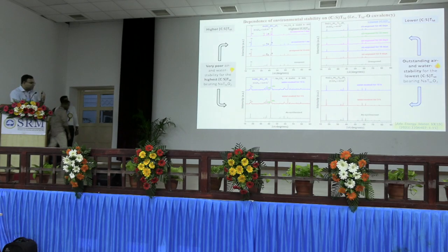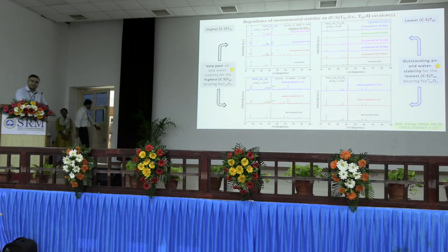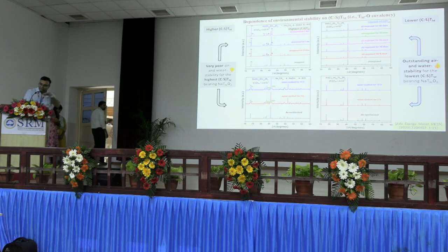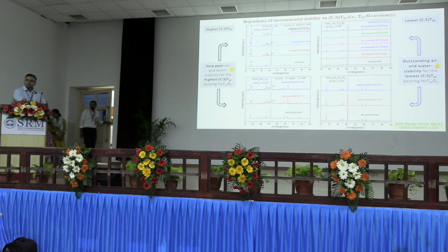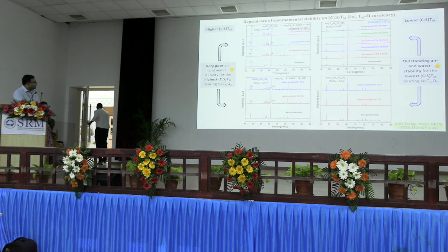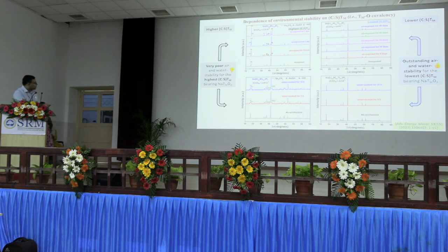Now, so how does that affect the air-water stability? So when I have a very high charge to size ratio in the transition metal layer cation combination, I expect it to be very poor in terms of stability, and that is indeed what we see. 15 minutes air exposure, it's totally gone. A lot of surface impurities, and we can see a structural transformation from O3 to P3 due to spontaneous sodium extraction. In just 15 minutes time, it is the same even after just 5 minutes.